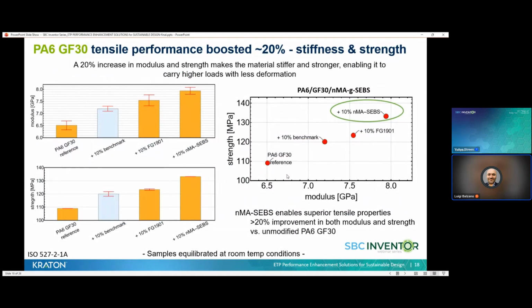The tensile properties of glass fiber-filled polyamide 6 modified with the malleated elastomers are quite interesting. When you take a bird's eye view of these slides, the bottom line is they show that by combining a hard material, polyamide 6, with 30% glass fiber, and a soft but functionalized material, for instance, a malleated elastomer, it is possible to obtain a material which is harder than the original. Quite surprising. Both modulus and strength tend to increase with the malleated elastomer modification, and the gains can be as high as 20% for the new solution NMA-SEBS that we are proposing.